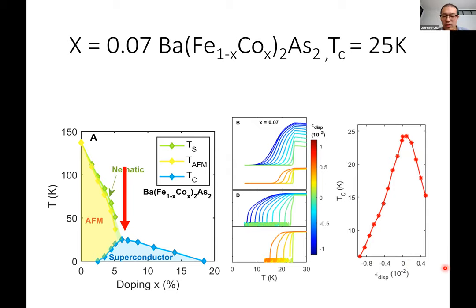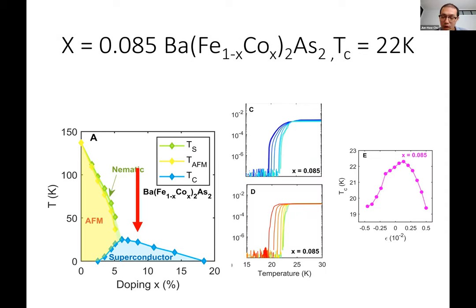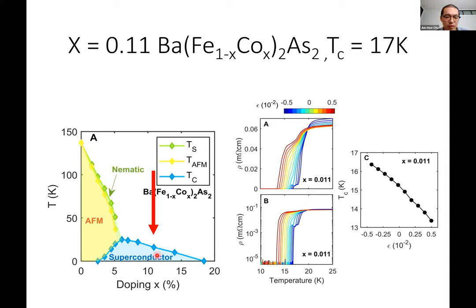This very strong suppression gradually goes away if you go to further overdoped samples, for example this 8.5% overdoped sample, where the Tc only decreased a little, from 25 Kelvin to 22 Kelvin. With the same magnitude of strain, the Tc only decreased from 22 Kelvin to 19 Kelvin. So much smaller suppression in comparison to optimal doping. And when you go to even more overdoped samples, around 11%, with a Tc around 17 Kelvin, you don't even see this symmetric suppression for both compressive and tensile strain. What you see is that the Tc just changes linearly with strain, and this is more like the pressure effect.